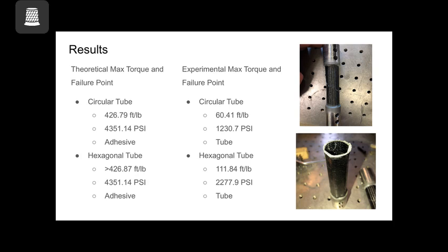For the hexagonal tube, we expected it to be greater than the circular tube, because due to the nature of the geometry of the hexagonal tube, the adhesive joint isn't purely under shear stress, it's also under compression and tension. This comes out to about the same 4,300 psi on the adhesive joint, and the estimated failure point was the adhesive joint.